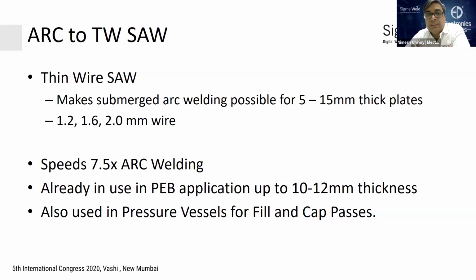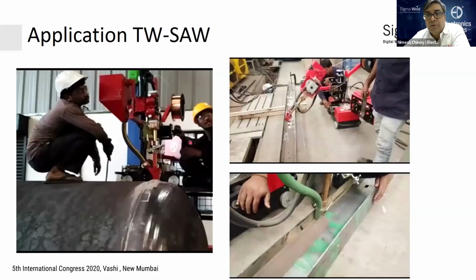And it's an already established procedure used in PEB, that is the pre-engineered building applications of 10 to 12 mm thickness, also in pressure vessels for fill and capping passes up to 5 to 10 millimeters. Just a couple of photos, videos to show you how it looks. This is a 6 mm pressure vessel being welded using thin wire SAW. Here you can see small girders being made, flanges being made by using thin wire SAW. The wire sizes are between 1.2 to 1.6 and specialized storages to reduce the amount of setup time.